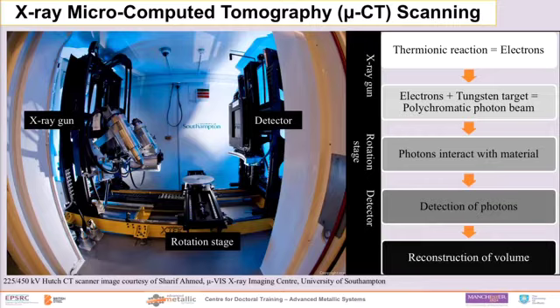Just to run through quickly how it works: in the X-ray gun, you use a high voltage to create a thermionic reaction, which generates a beam of electrons, which crash into a reflection tungsten target, creating a polychromatic beam. This beam travels through your sample, which sits on a rotational stage. The stage rotates so that the beam is passing through at multiple angles. It can also move in the X, Y, and Z axes. The resultant photons or X-rays are then detected by the detector, and the software is able to reconstruct the volume.